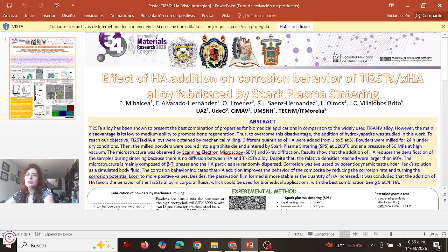In order to reach our objective, the titanium 25 tantalum and hydroxyapatite alloys were obtained by mechanical milling. Different quantities of hydroxyapatite were added, from 1% to 5% atomic percent. The powders were milled for 24 hours under dry conditions. Then the milled powders were poured into a graphite die and sintered by spark plasma sintering, also known as SPS, at a temperature of 1200 degrees Celsius and under a pressure of 50 megapascals at high vacuum.